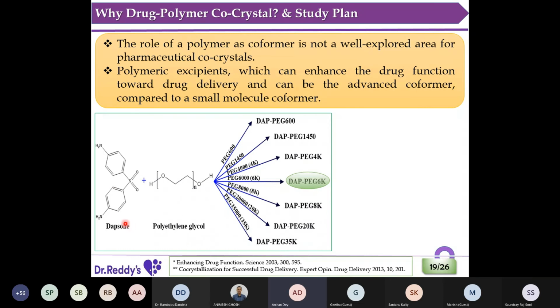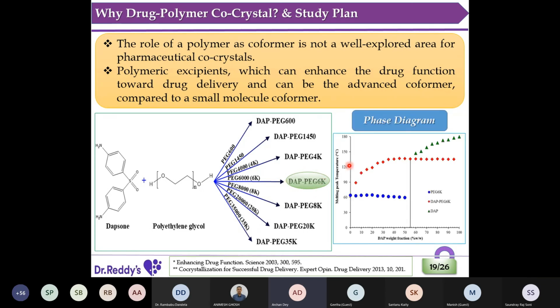For the Dapsone, we are trying to co-crystallize with 7 different grades of PEG, starting with a low molecular weight 600 to 35,000 molecular weights. And we standardize our protocol with the 6K. So first we did a phase diagram.